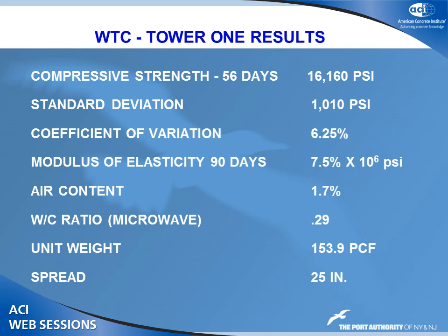We tested this. We do all the testing. There's nothing in it for us to make up data. We don't get paid any more whether the coefficient of variation is 7 or 17. That's what it turned out. But I tell you, the same concrete producer can give you a coefficient of variation of 14 for 5,000 psi concrete. What's the moral of the story? You've got to pay attention to what you're doing. And when he did, he produced fantastic, consistent concrete.